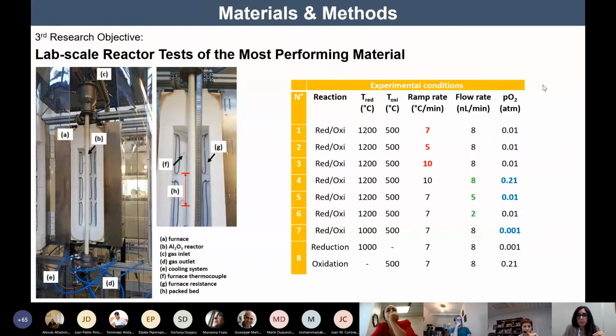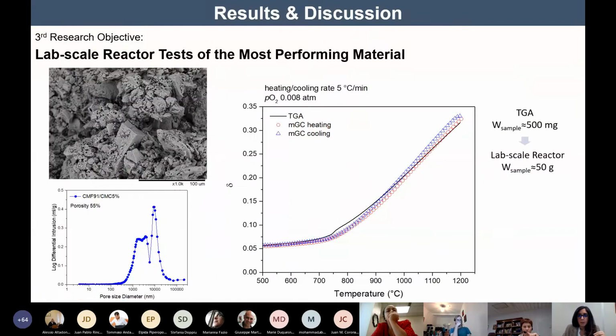And several experimental conditions were investigated. We changed the ramp rate, the flow rate, and the PO2. We selected 5% carboxymethyl cellulose (CMC) containing pellets that had a porosity of 55% after sintering. And this is the result.